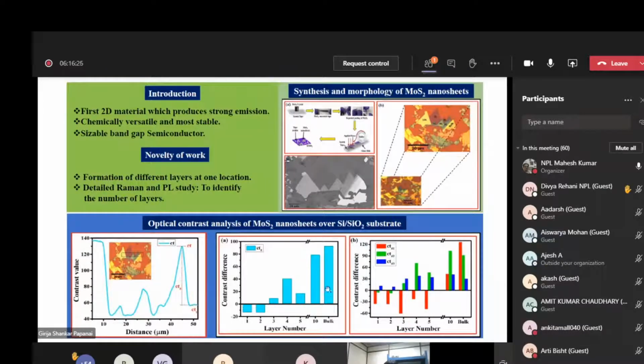From this figure, you can clearly see the layer identification by using the contrast analysis, but if you look at this one layer and two layer, there is very little difference. So further, we split this image into the three different channels, that is red, green, blue channels, and here you can easily find out the difference between each layer.